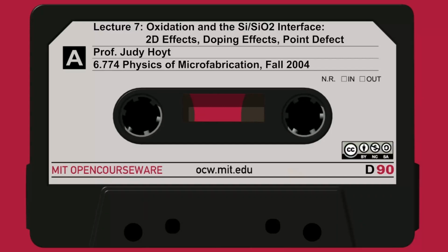Here's an actual simulation of oxidation-enhanced diffusion. What happened was the surface started out by being implanted uniformly with a certain dose of boron. So I have a very thin layer of boron up near the surface. And then we grow a pad oxide, and we grow a nitride layer on the left. So on the left, there is going to be no oxidation taking place. We put it in the furnace at 850 for an hour. And you see an oxide has grown on the right, none on the left, which makes sense.